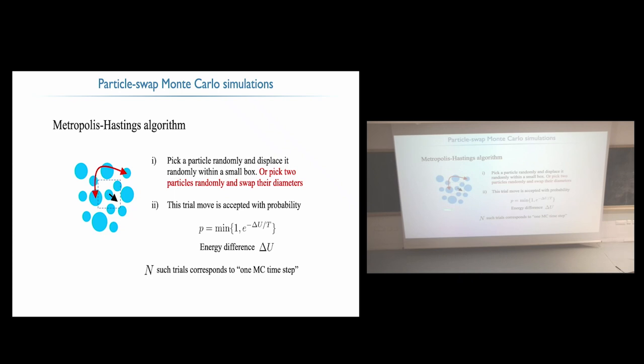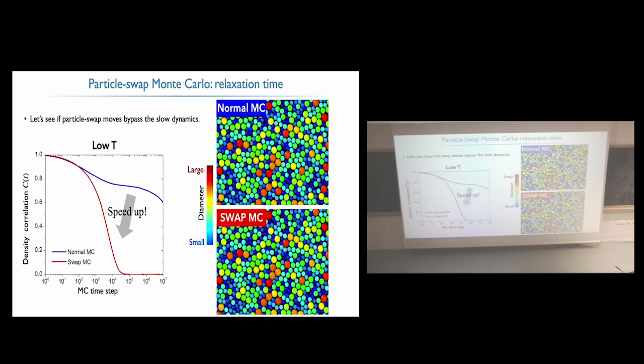Remember, the particles have different diameters to avoid crystallization. So you pick two particles at random, and you try to exchange their diameters. Again, you compute the energy before and after, you do the Metropolis filter, so you're sure that you're in equilibrium. And then it means that you're also sampling equilibrium configurations. So I think you would all agree that this is a very small perturbation to the initial algorithm. Let's look at what happens in time. Again, this isn't physical, but at this point, we're not interested in the physical dynamics. We just want to get equilibrium samples close to TG.